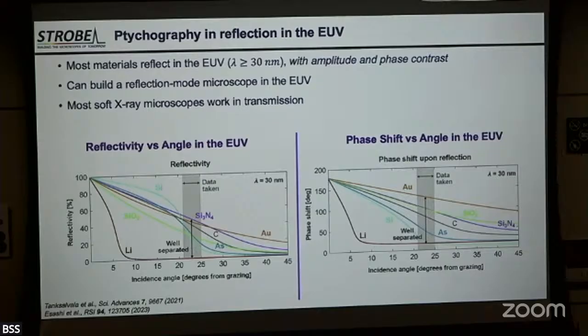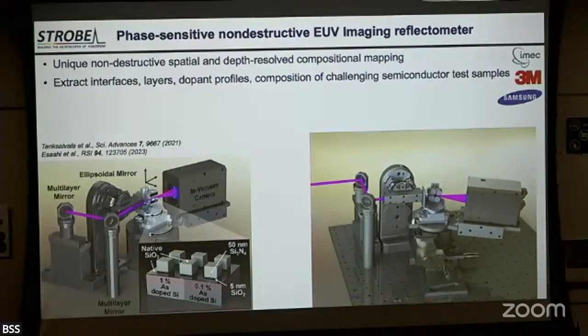Those of you who might have seen images from a synchrotron in the soft X-ray region: soft X-rays, the index is low, and so you don't get any reflected beam. So all the microscopes work in transmission like a TEM microscope. The extreme UV still reflects. So you can make a microscope where you can take a part of a heterostructure, or a magnetic multilayer, and stick it in your microscope and still get a reflection. So we can build a microscope. And then if we have a coherent microscope, we get to separate different materials by their reflectivity and also by their phase change on reflection. So suddenly you get a lot of information that you can use to build a model and learn what the structure looks like.